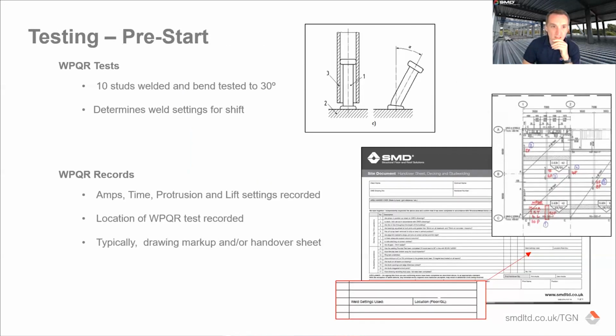So that's the weld process, and then I'm just going to talk quickly about tests. So pre-start, how do we make sure the studs provide the weld that we need and hence the resistances that we talked about earlier in the presentation. So you start with what's called a WPQR test. That's 10 studs welded and bend tested to 30 degrees. That determines essentially your settings for the day within the ranges that were in the WPS that I talked about earlier. So that will give you your amps, your time, your protrusion and your lift settings. You'll record them on a drawing and you'll carry on with your shift on the basis the 10 studs welded and bend tested have passed the 30-degree bend test.